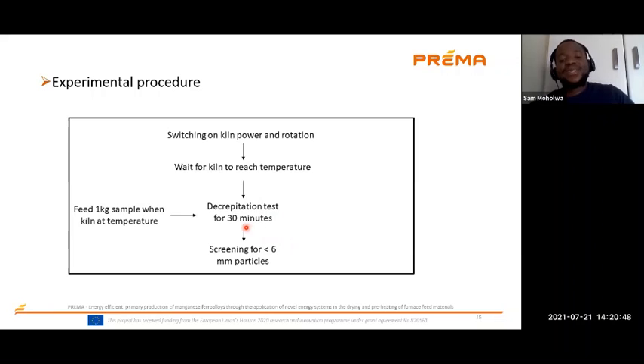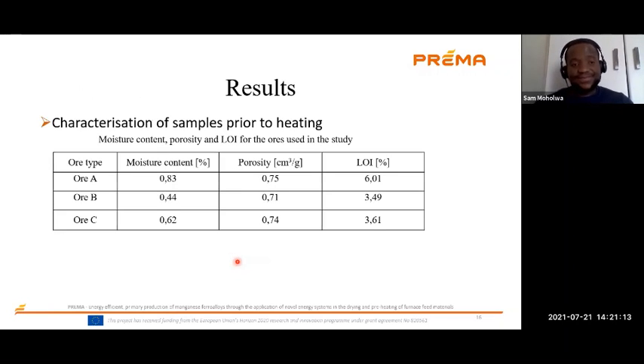Then the sample was left to rotate and heat for 30 minutes. After heating, the sample was then allowed to cool inside the kiln overnight. Then the following day, the sample was removed from the kiln. Then we screened this sample to get particles that are less than 6 millimeters to determine the decrepitation index. Now we get into the results.